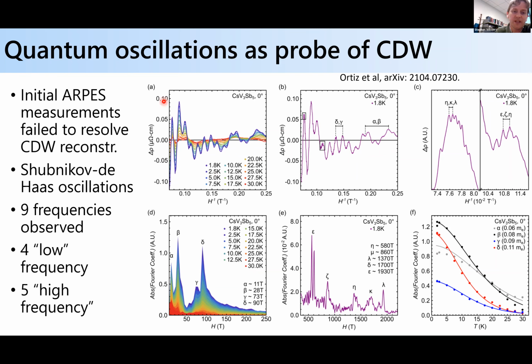So one of the things we tried was to look at quantum oscillation measurements in the form of Shubnikov-de Haas oscillations. In particular, we looked at the cesium vanadium-3 antimony-5 system. Here is data showing that we can see Shubnikov-de Haas oscillations, as it's a high mobility material with very low electrical resistance. At 2 Kelvin, above the superconducting transition, the rho naught is something like 0.1 microohm centimeters. So you can look at oscillations up to 14 Tesla at 2 Kelvin. You can see they get damped out as a function of temperature.